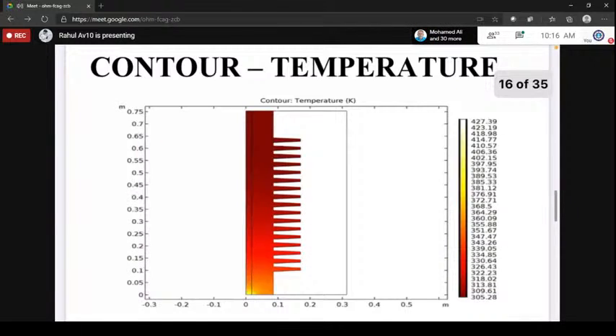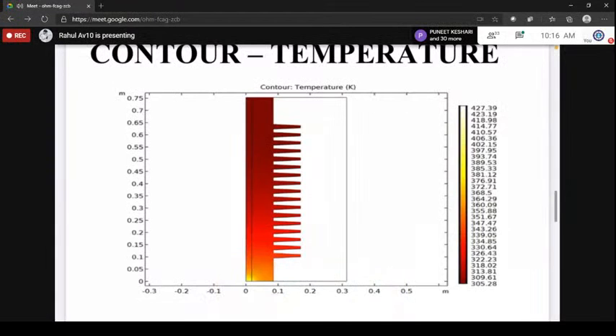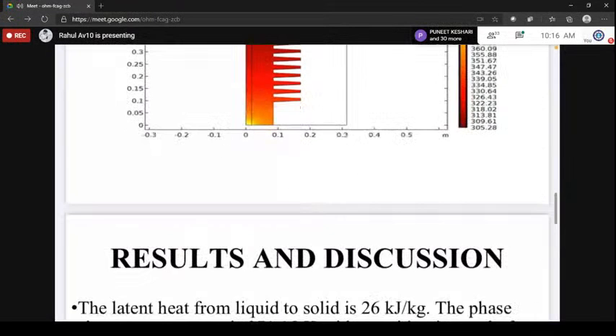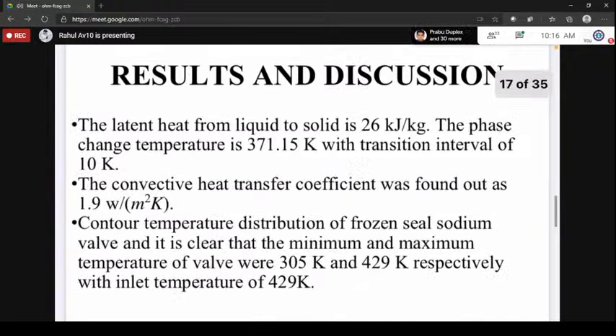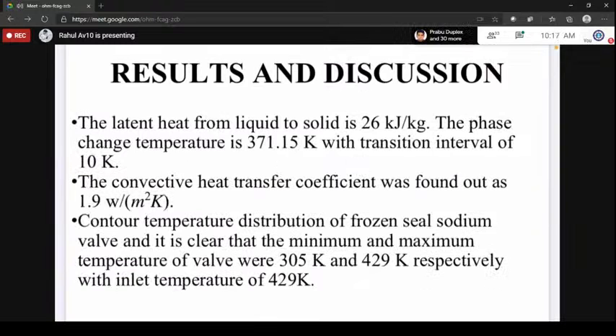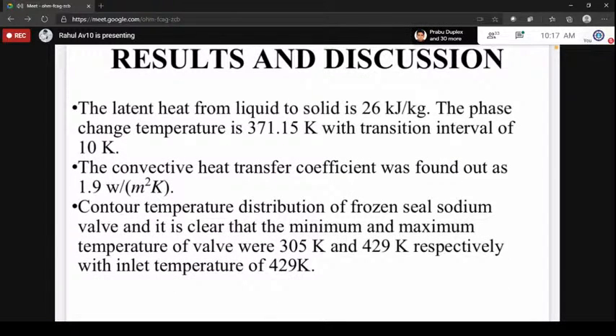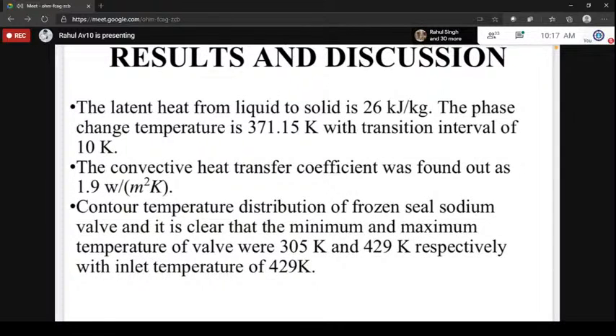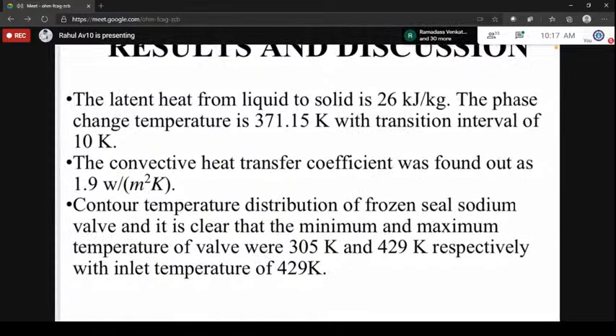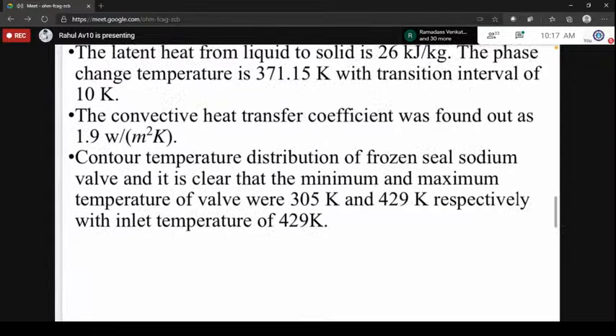And this is the contour temperature on the front axis. So the result for the first case is that the latent heat from liquid to solid is 26 kilojoule, and the phase change temperature is 371.15 Kelvin with a transition interval of 10 Kelvin. And the convective heat transfer coefficient is found to be 1.9 watt per meter square Kelvin.